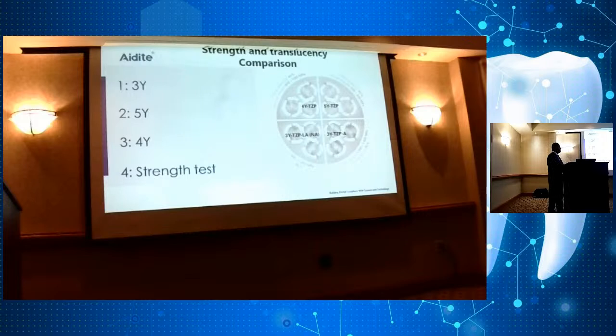And you'll notice here, it's really blurry back here, but you'll see that when you transition from 3Y, 4Y to 5Y, you lose a little bit of the structure, relatively speaking, but you gain translucency. Okay? So if you were to use a 5Y material, which is predominantly cubic material, you are going to gain a lot more translucency, but really lose the strength.